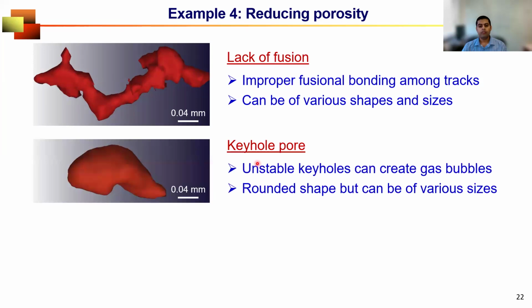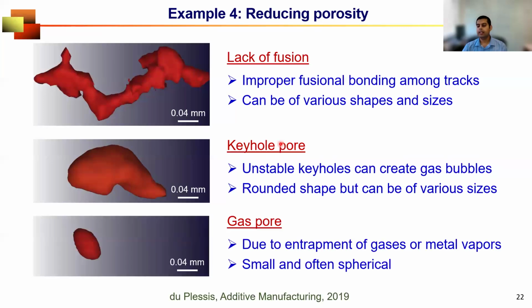Second, often we perform additive manufacturing in keyhole mode. What do I mean by that? The energy density is so high that it forms a vapor cavity during the process. And if that vapor cavity or keyhole is unstable, that will break and generate a lot of gas bubbles that will end up creating porosities. And the third one is gas porosity, where the shielding gas or metal vapor are trapped